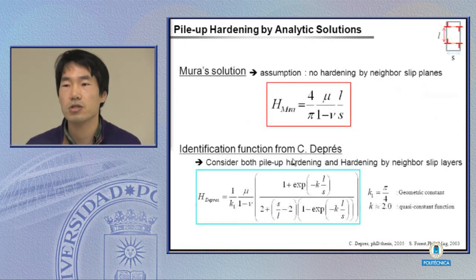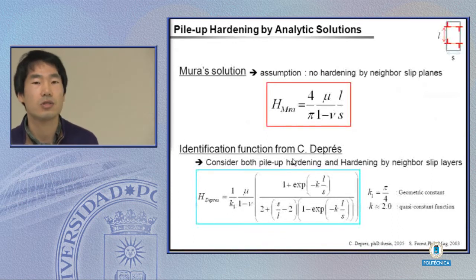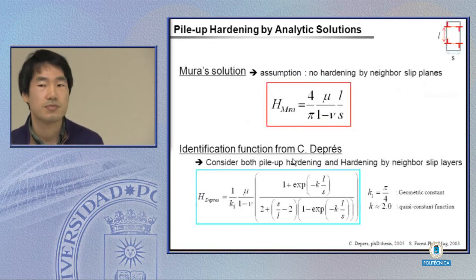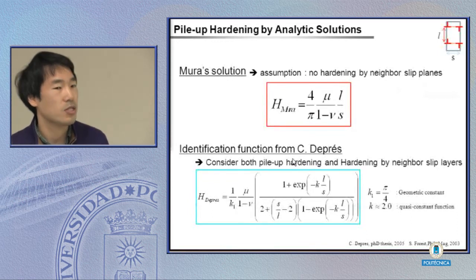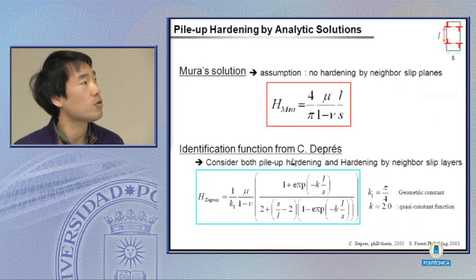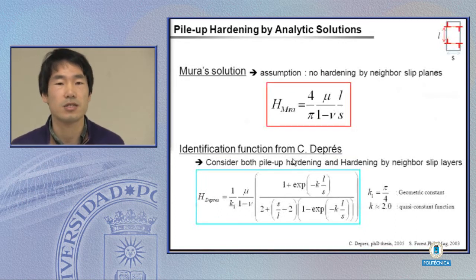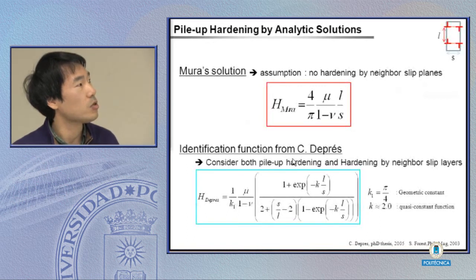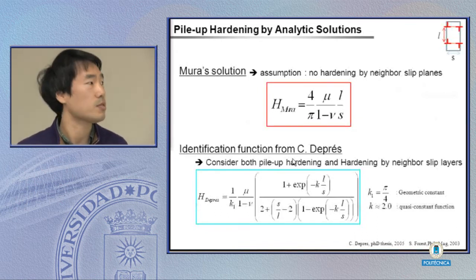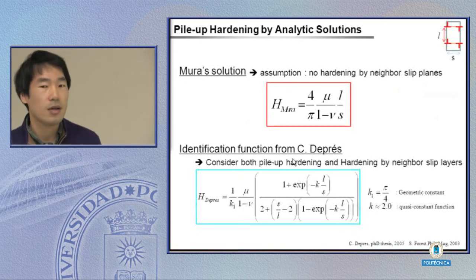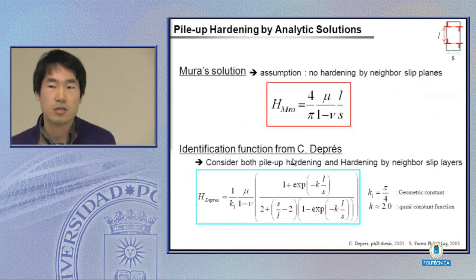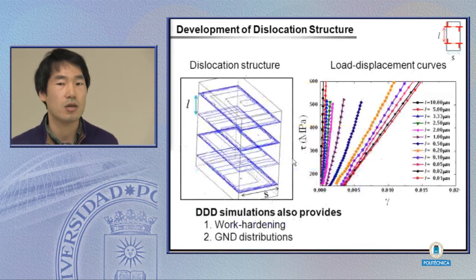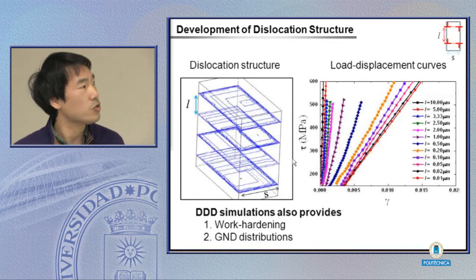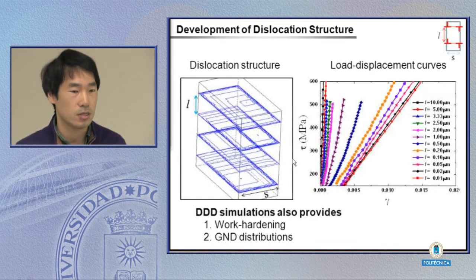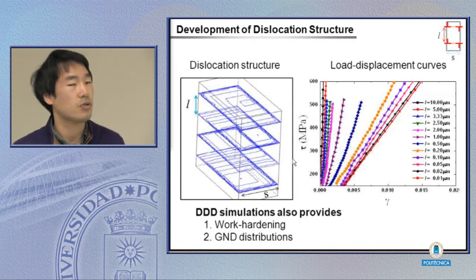Before showing you dislocation dynamics result, I'd like to introduce you some of the analytical solutions for these systems. At first, the Mura's solution gives the analytical solution for this kind of multi-slip pile-up cases. However, in this case, there is no consideration of the interaction between the slips. On the other hand, the Christophe Defray suggests some alternative analytic solution, which includes both the pile-up and the multiple slip planes and the interaction between the slip planes.